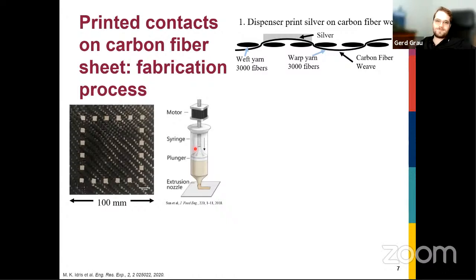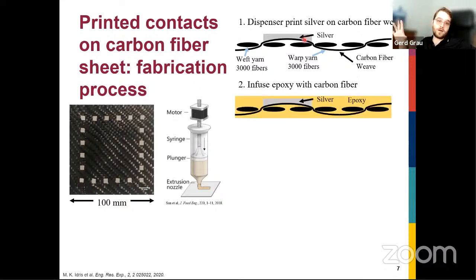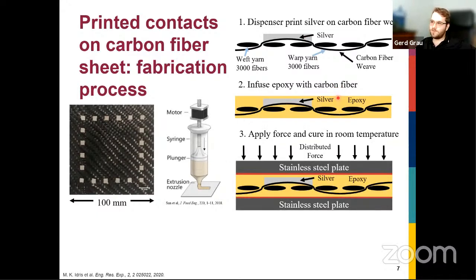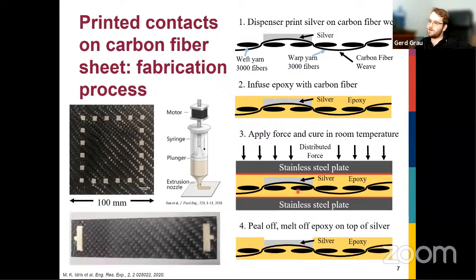But let's say we've optimized this and we can actually print the silver. So now we have silver printed on our carbon fiber. We can cure it. And then from then on, we can just use traditional carbon fiber composite manufacturing techniques. So we can infuse it with epoxy, and then we can, for example, compression cure. We've used vacuum bagging as well. So you can use traditional methods to then finally create this composite.